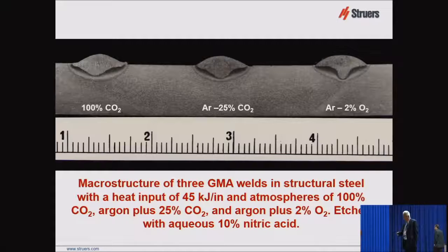with my arm. These are three gas metal arc welds in structural steel with a heat input of 45 kilojoules per inch. And the atmosphere is 100% CO2 here. And then this one is argon with 25% CO2. This is argon with 2% O2. And I've etched this with 10% nitric in water as a good macro etch. And you can see how the penetration of the weld into the base metal has been altered by the gas content that was being used.